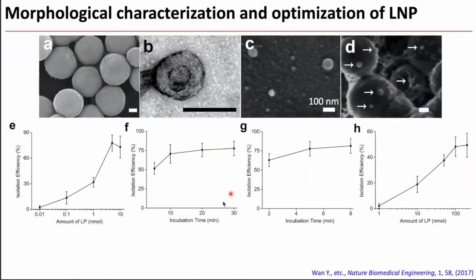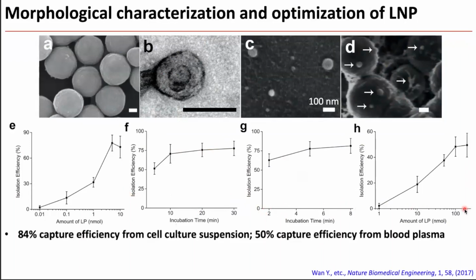As an engineer, we actually optimize this process. For example, we optimize the amount of labeling probe, the incubation time of the labeling probe, the incubation time of the capture probe. And also what we found is when we switch from cell culture derived EV to plasma samples, we actually need to increase the labeling probe by almost an order of magnitude to account for the lipid binding proteins within the plasma sample. So in the end, what we have demonstrated is we can have about 84% capture efficiency from cell culture suspension and about 50% capture efficiency from the plasma.